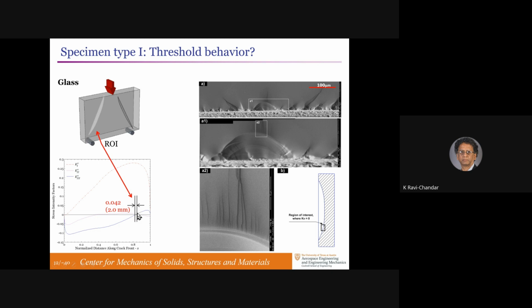The two vertical lines here delineate the 2-millimeter region of the box, over which there's a very small variation in K3 over K1, but it spans the range where the threshold behavior was observed by Sommer. So if the Sommer threshold is true, we should see flat crack between these two lines, and then the angle formation beyond that point. But this is what we actually saw.